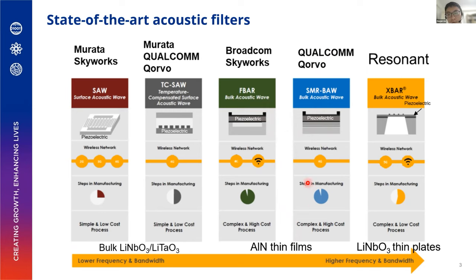So the material being used for this is aluminum nitride thin films. So this is the industry dominant design and materials. And then recently there's a company called Resonant. So they've designed this X-bar geometry, where it's also kind of a bulk wave resonator, but with a simpler structure because it only uses the top electrodes, the patterns, to excite the waves. So they use this lithium niobate thin plates.